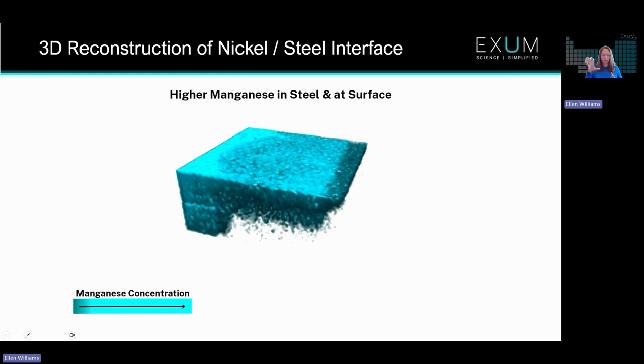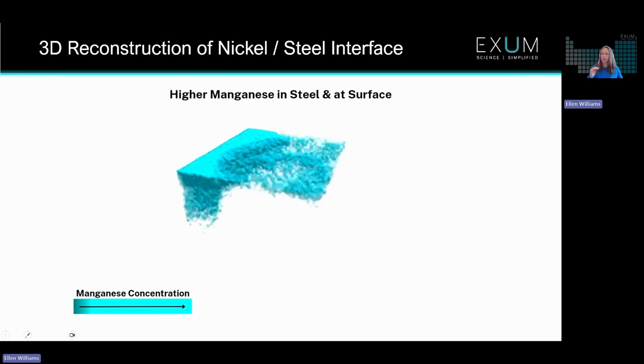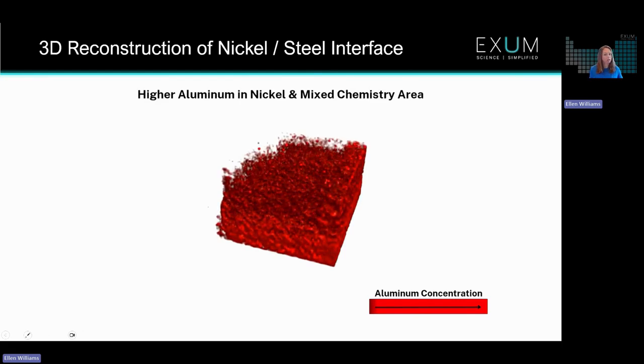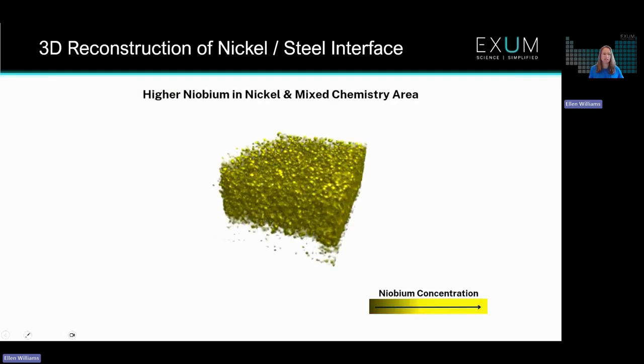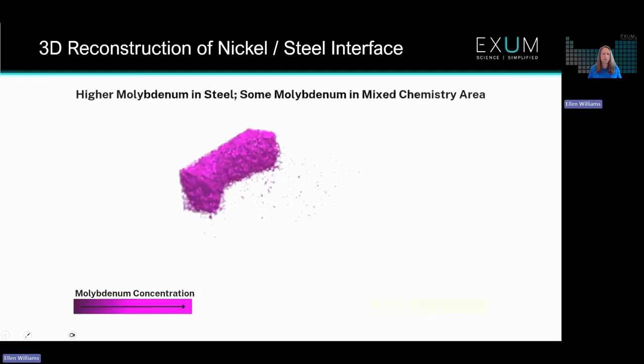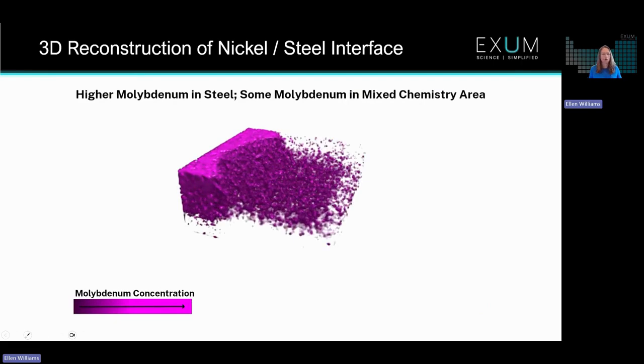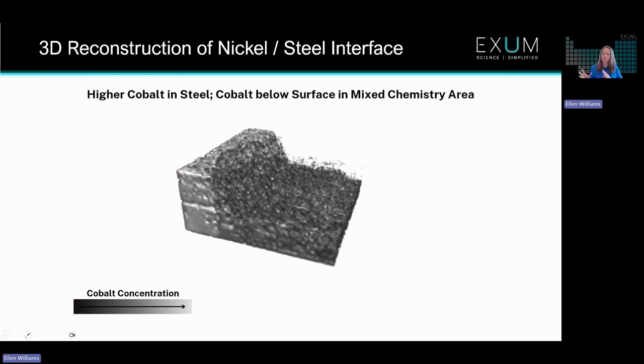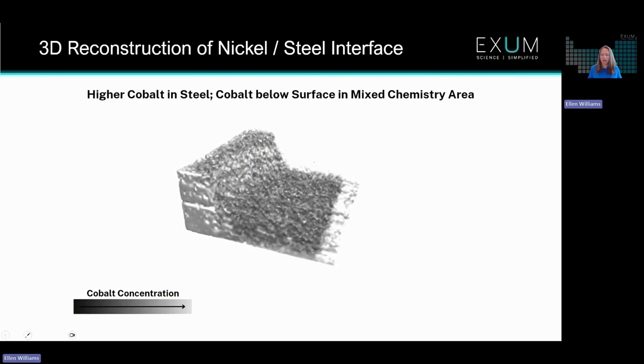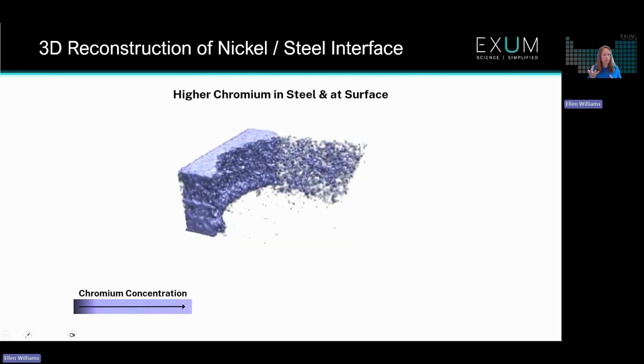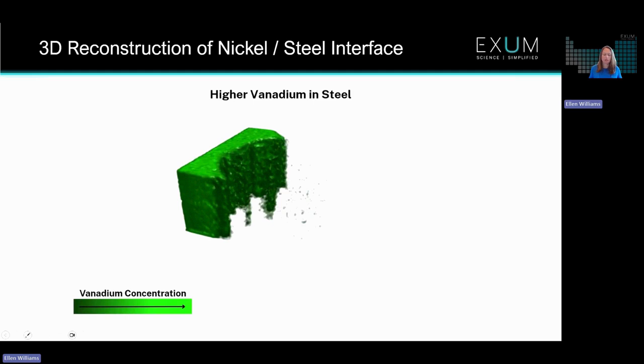So again, essentially what we did was just with those elemental maps, repeated that elemental mapping process, ablating away hundreds of nanometers in this case per layer, so that we created a depth of 10 microns that was validated with a microscope measurement. And then because each one of these voxels contains that full mass spectrum of data, we're able to look at all of these different elements that we detected and see, are they concentrated in the steel or the nickel side? Are we seeing them in the melt pool in that area of mixed chemistry? Are there changes from surface to subsurface? And it gives us a much more thorough examination than just the surface analysis alone.